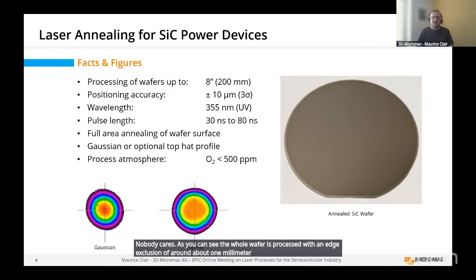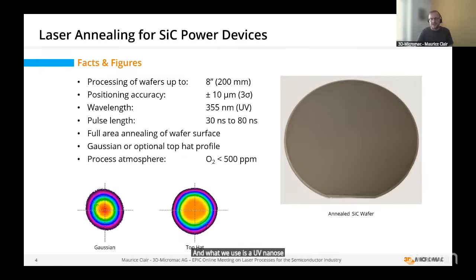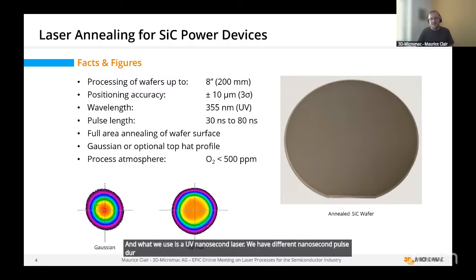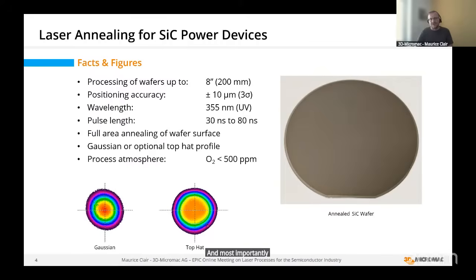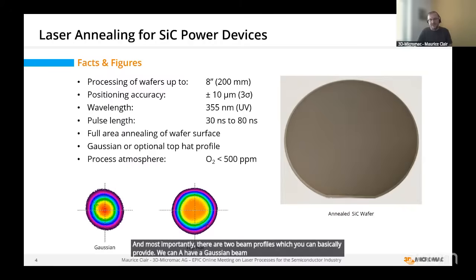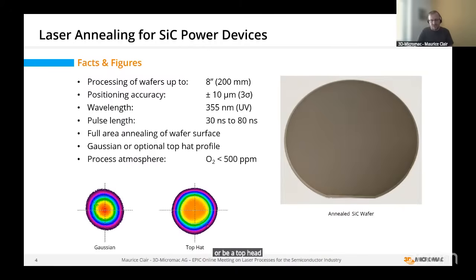And what we use is a UV nanosecond laser. We have different nanosecond pulse durations to adjust the physical result of the chemical reaction. There are some diffusion processes involved. And most importantly, there are two beam profiles which we can basically provide. We can A, have a Gaussian beam, or B, a top hat. What's the benefit of the top hat?